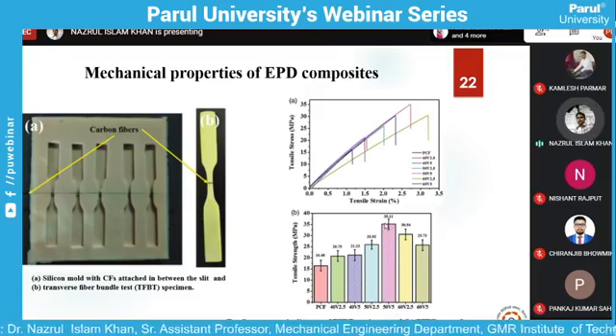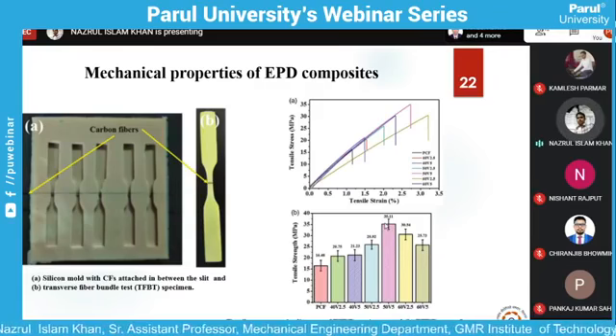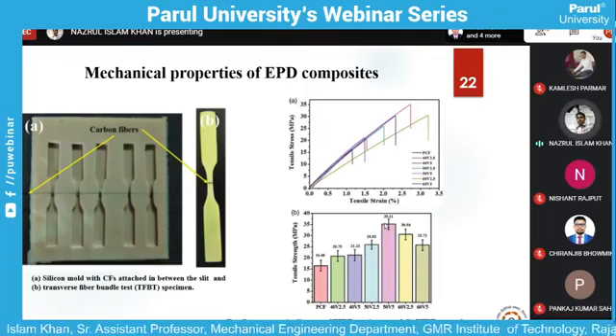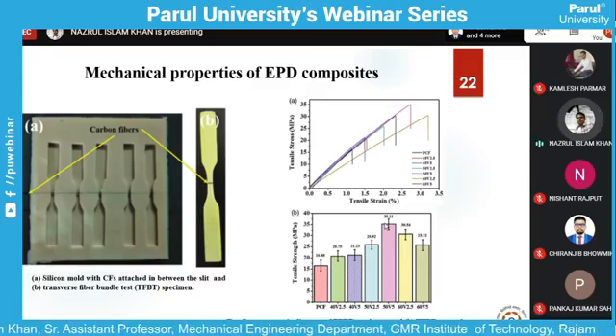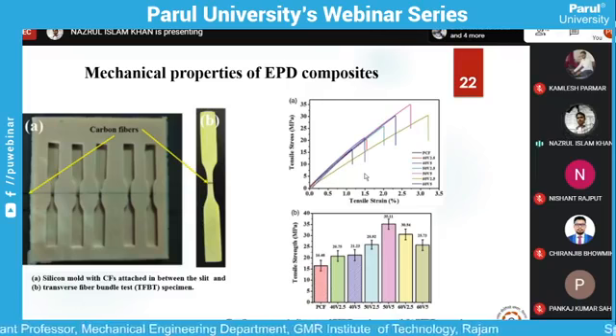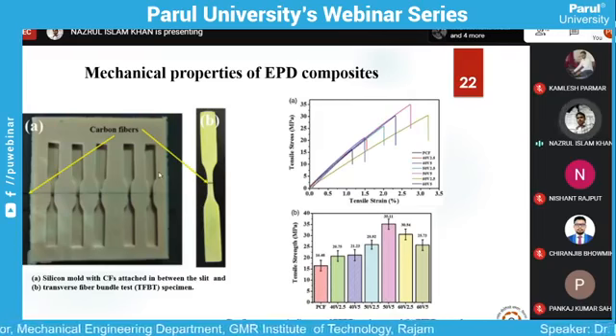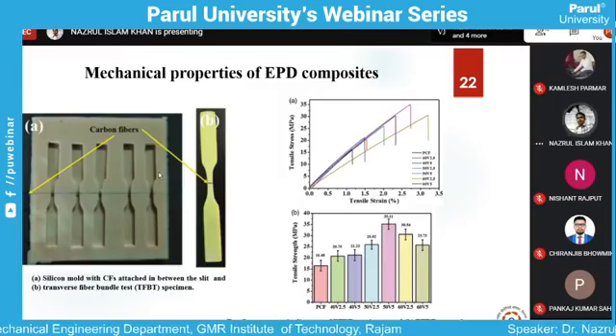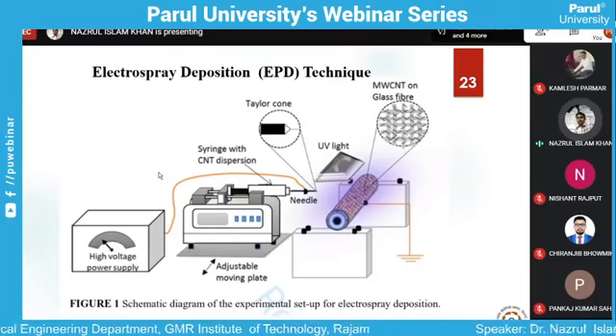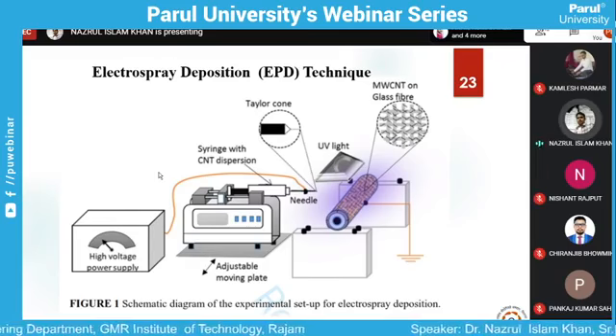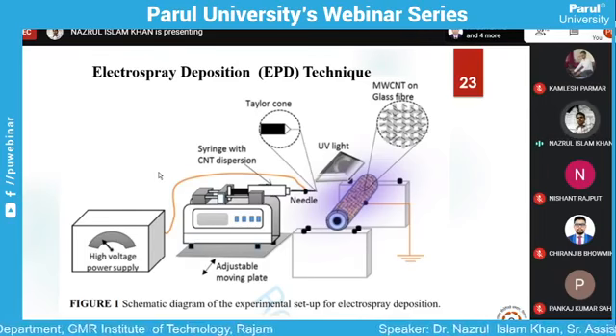And again, you can tell me, oh, it is very poor mechanical properties, 35. Yes, it is very poor, but this testing was just to confirm at what voltage this higher interfacial adhesion is taking place. But generally, if you want to measure the tensile strength, we do the testing along the longitudinal direction. So another technique that is very, very fast, because whatever technology you develop, that should be industrialized also.